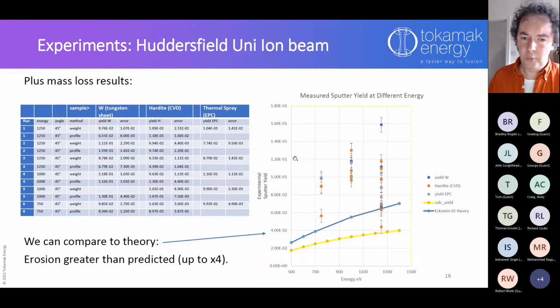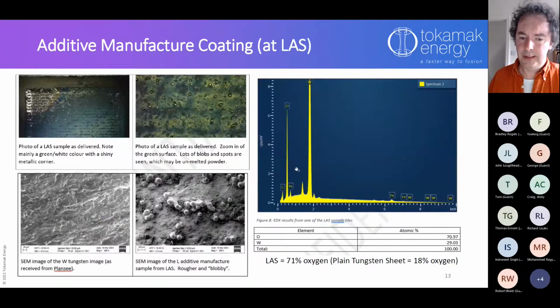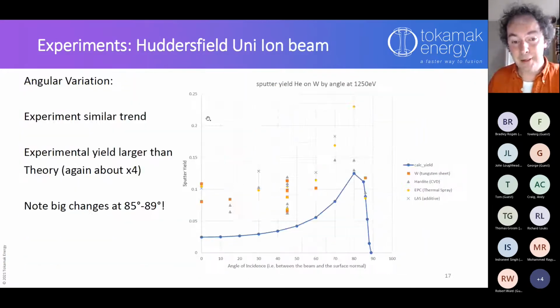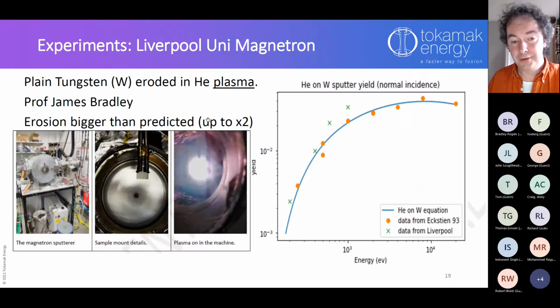Let me just scroll back a sec, because I think I was going to say something about the oxide. Oh yeah, I haven't got a photo of these samples. I thought I maybe had a picture of it, but as soon as you expose these additive manufacture samples to the ion beam, when you take them out, their surface is all really shiny. What's happened is that the ion beam has cleaned off the oxide, and we know the oxide has a much smaller binding energy than the tungsten that's in the lattice.